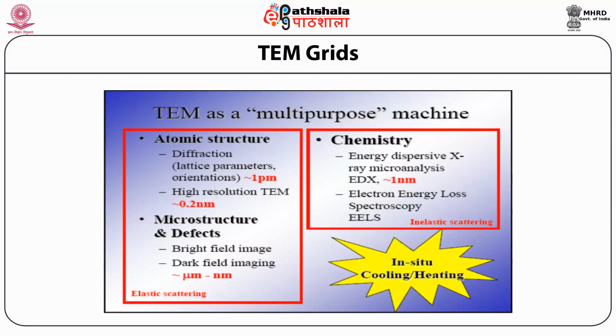Transmission electron microscope is basically a multi-purpose machine. One can carry out diffraction studies, which will tell you the atomic structure, lattice parameter, orientation, and high resolution TEM. On top of that, we can obtain bright field images and dark field images, by which we can study their microstructure and defects. And one can also do chemistry by energy dispersive X-ray analysis, which is called EDAX, or electron energy loss spectroscopy, which is called EELS. So in this way, TEM is a very multi-purpose machine where one can find out their microstructure, defect, atomic structure,